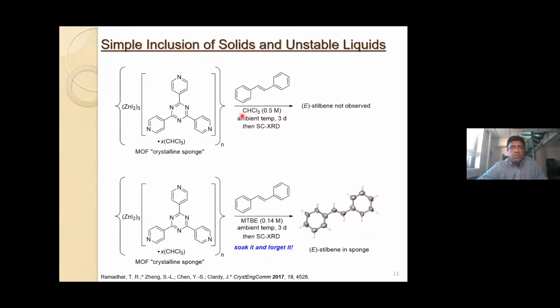So I thought, well, why don't I switch the solvent from chloroform to MTBE, methyl tert-butyl ether, which is polar enough to dissolve E-stilbene, but it's not going to be as strong as chloroform. So by switching the solvent, I was able to include E-stilbene at a lower concentration inside of the crystalline sponge, and I was finally able to observe it. And it was very easy to do. You just solubilize this in MTBE, add it, soak it 3 days, and it was good to go for X-ray crystallography.